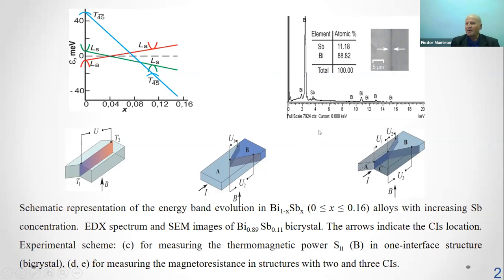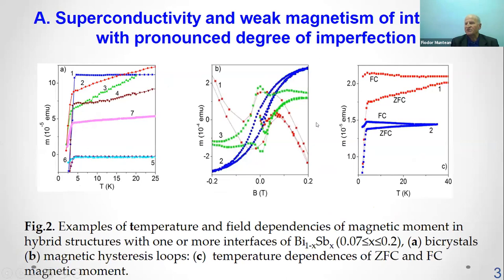Figure one and figure two present temperature and field dependencies of magnetic moment of our structure highlighting a single or two superconducting transition. The temperature dependencies of magnetic moment are characterized by increase of the difference between the zero field cooled and field cooled signal followed by magnetic field expulsion.